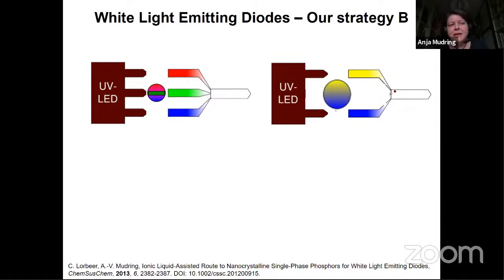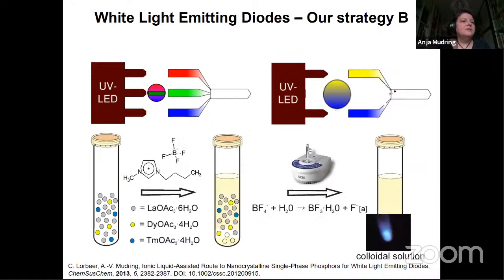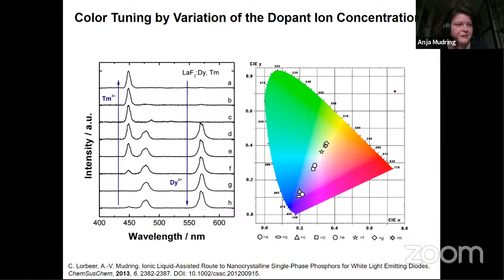That's a bit complicated. It might actually be a lot easier to use the concept that many LEDs use right now, where you have a blue light emitting LED chip covered with a phosphor that contains cerium, which gets activated by the blue light and emits yellow light. So combine yellow and blue to make white. And you can do that by taking dysprosium and thulium, same reaction. So I see it starts getting boring. And you can again hit the white spot. But what is also quite nice, you can play a bit around with the excitation energies and tune the light into something that is more bluish or something that is more yellowish.